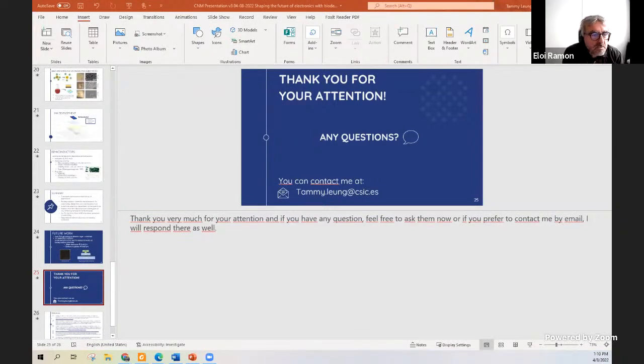Yes, thanks, Luis. Today, for example, silver commercial inks require 30 minutes of sintering in a conventional oven. So it's still not really interesting, especially when thinking of printed electronics in roll-to-roll processes, because roll-to-roll is a continuous manufacturing, so it's expected to use some kind of technology faster than a conventional oven, because 30 minutes is too much. But the idea here was to try to reduce or avoid sintering that requires too much energy. But for sure, 11 days is not practical. It's just an academic game. It doesn't have any sense.